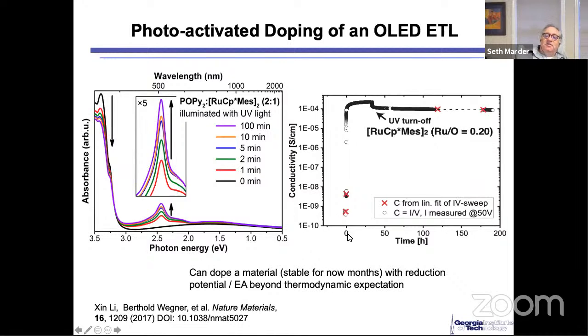Now, here is the thing that is kind of interesting. I've talked about this as a photo-induced electron transfer. Now, for those people who have worked in solar cells and in other things, if you get a photo-induced electron transfer and you get a charge separated state that lasts a microsecond, that's considered a very long-lived CT state. Oftentimes you get ultra-fast electron transfer, and then on the order of nanoseconds or tens of nanoseconds, you get recombination. And this is one of the things that we fight when we are making solar cells. And as I said, our system is 0.4 of a volt uphill. So what do we actually observe?